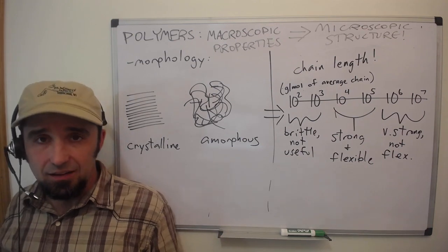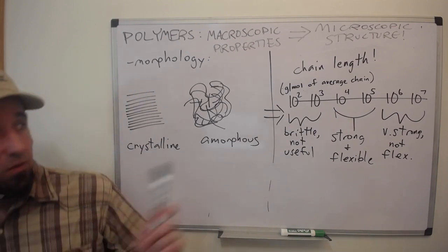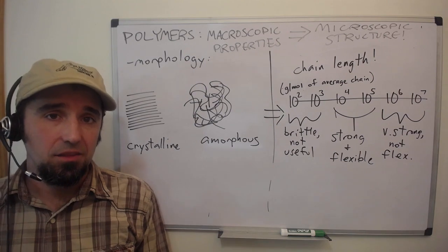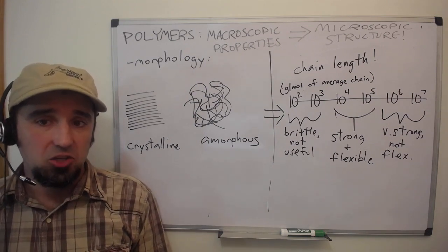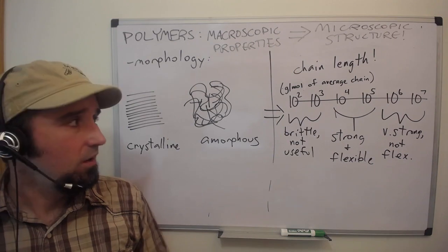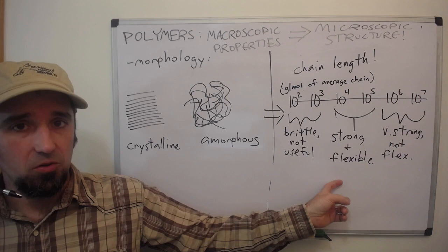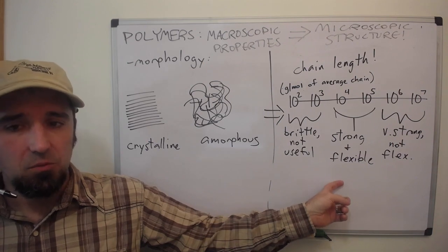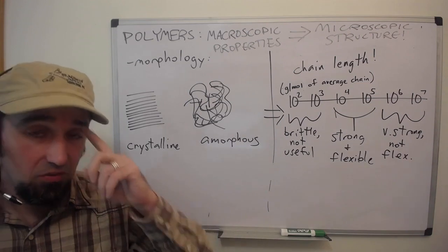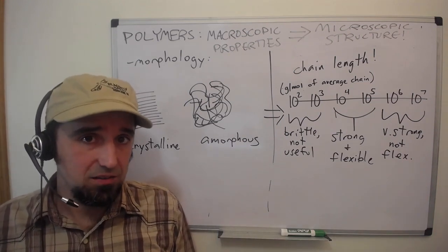So the chain lengths for polymers are really, really long, right? So this is a log scale number line. And if we look at something like nylon, the optimal length for a nylon chain in terms of Daltons, or grams per mole, is about 10,000 to 100,000 grams per mole, and they'll vary a little bit. But that's kind of the range in which nylon is both strong and flexible. And if you think about a nylon rope, then yeah, I need it to be both strong and flexible.